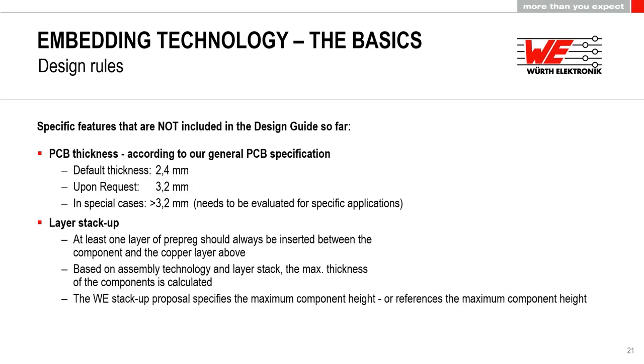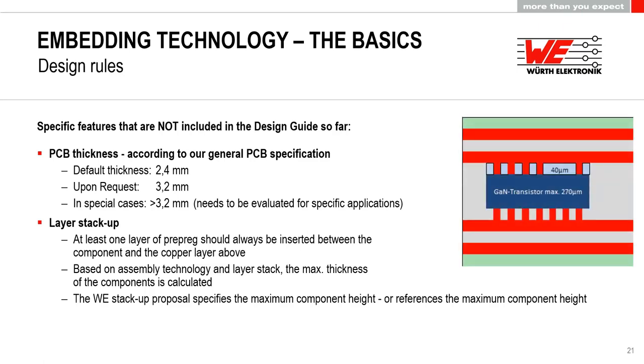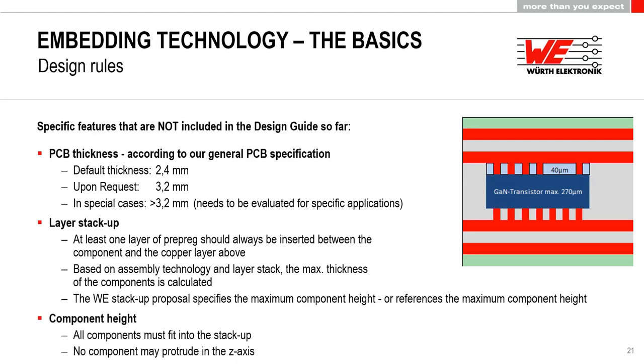You will see later that you will get a stack-up proposal from us. In this stack-up proposal, you either see the maximum component height already, and we calculate the stack-up height out of the maximum component height, or vice versa. You give us a maximum thickness of the stack-up, and based on that we calculate backwards and give you an impression of how thick the thickest component might be, so that everything fits inside of this stack-up.